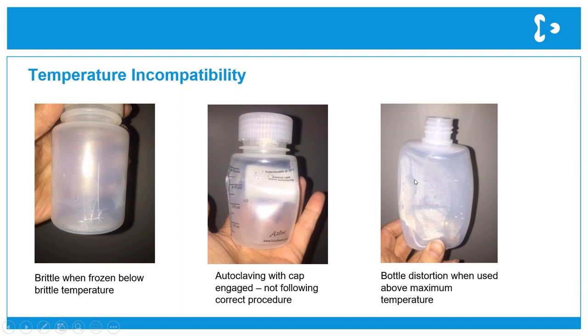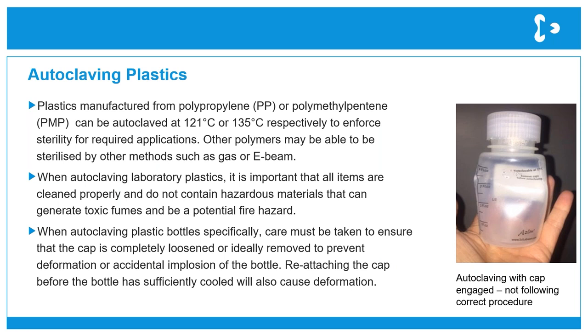Here you can see you've got distortion. The bottle's been taken above a temperature that it can ordinarily withstand, and it's caused a collapse of the bottle. So as you can see, choosing the correct polymer with the right resistance criteria, in this instance temperature resistance, is really very important. Focusing on autoclaving for a moment, as more and more people are autoclaving and reusing product where possible, polypropylene can be autoclaved at 121, and PMP, which is polymethylpentene, can be autoclaved at 135 degrees centigrade. In addition to autoclaving, there are other methods that can be used to sterilize plastics which can't be taken to such high temperatures.